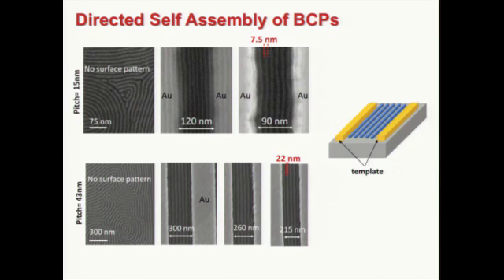Well, obviously, for a device, we need them sorted parallel together. If there is no feature on the surface, they form such a random morphology. But to have them directed in a self-aligned way, we need templates. Here in this work, we use gold lines, as you can see in this schematic. The reason that we use metal here is that later we can use them as external contact to the MoS2 channel. So it's 2-in-1. It works as the template to have parallel lines, and also later we connect them to the source drain bias.